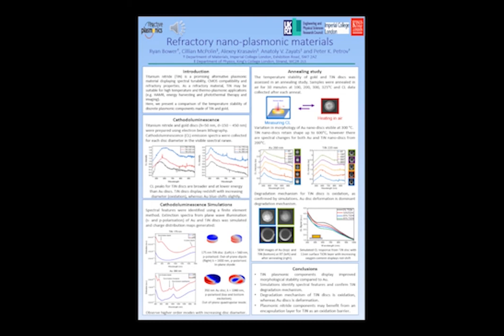So after we characterized the properties of room temperature titanium nitride and gold discs, we completed an annealing study to assess their temperature stability and to observe any changes in the cathodoluminescence response or the morphology. In the annealing study, we heated samples for 30 minutes at a time at increasing temperatures from 100 degrees. And after each anneal, we measured the cathodoluminescence response and assessed whether there were any changes in the morphology of the film using SEM. And we see that there are different degradation mechanisms for the titanium nitride and the gold discs. The gold discs display changes in their shape from 300 degrees, whereas the titanium nitride retain their shape up to temperatures as high as 600 degrees.